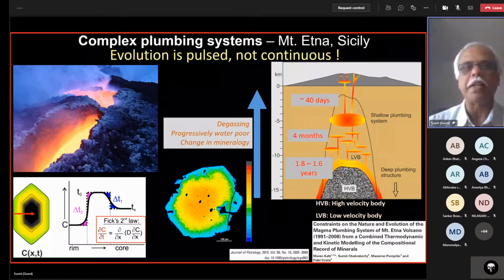And what happens there is the mineral changes, but the behavior remains exactly the same as what we were talking about before. So what you are now looking at is olivine. And again, during this magmatic evolution, olivine grows in different pulses. And once you have different growth zones, things diffuse between those zones at those high temperatures. That's shown here on this concentration profile diagram. And you see it much better on this element map here. This is again the magnesium concentration in an olivine crystal from such a lava flow. And what you see immediately is that it is not one smooth continuous change. So in the middle you have quite high magnesium, reddish orange. Then you have a rim with something yellowish, so it's decreasing. Then it goes to green and then to blue. So it seems to happen in kind of pulses with diffuse boundaries between each of those regions.